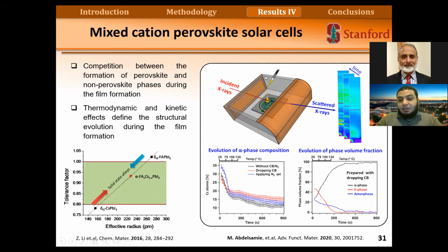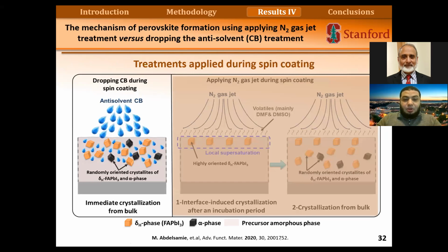So I try to employ in situ X-ray scattering in order to get information about the phases that are formed and the composition, so we could know what the composition is and how it changes over time. And also we could get the phase fraction. So the film has an amorphous phase, a delta phase and an alpha phase, and this changes in fractional time until we reach the final state. And with in situ techniques, we could track all these changes, and we could understand how these techniques are used to tune the microstructure. So these are the final thoughts that we reached for the dropping antisolvent.